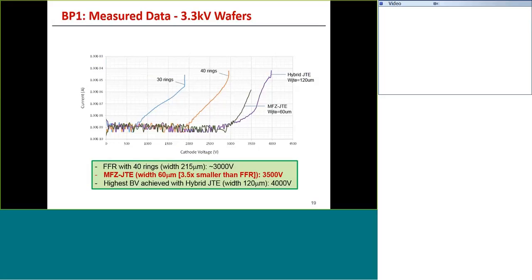You can see here that as we change the edge termination from 30 rings to 40 rings, the breakdown voltage increases from about 2,000 volts to 3,000 volts, but that is still not sufficient. By going to MFZJTE with 60 micron width, we're able to hit our target of at least 3.3 kV. The leakage current is usually spec'd at 100 microamps, which is 10 to the minus 4 on this graph.